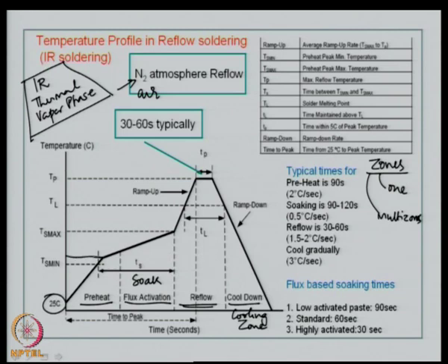So, typically somewhere here could be your first earmark for defining the preheat zone from room temperature. So, this could be typically from 25 degrees centigrade to, let us say, 150 degrees centigrade, depending upon your TG of the board. You want to activate the board, you want to activate the interconnects, the copper, and then you are also removing moisture from the components.